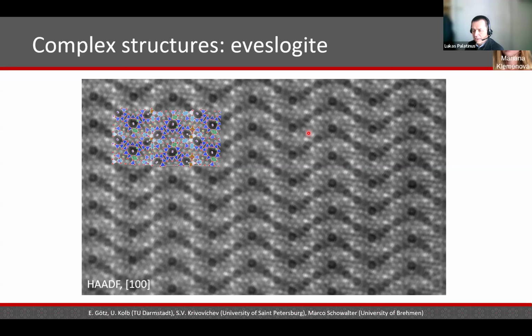So you can't say that if you pick crystals smaller than, I don't know, 50 nanometers, that you will essentially suppress the dynamical effects. That's not how it works. In practice, we usually do not have that much choice over the size of the crystals. And I can say that the proper treatment of dynamical effects allows getting good refinements even from crystals that are relatively thick. So a crystal that is 150 or 200 nanometers thick, that's already a relatively thick crystal for electron diffraction, and even then it's possible to get sometimes good results.